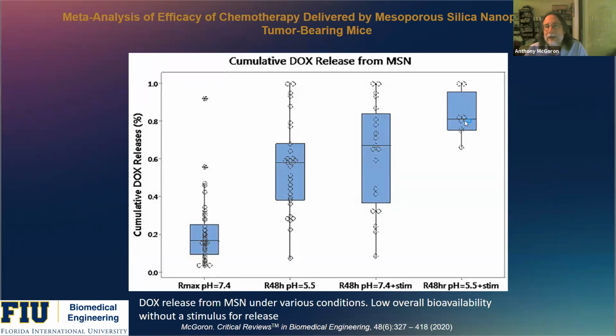If they make it into the tumor and we stimulate the tumor with heat, or maybe it's stimulated because of the thiol conjugation, so they're released due to glutathione in the cells, we get a much faster release. But remember, a very few percentage of the particles are actually making it to the cell. So if they don't make it to the cell and they don't get endocytosed into the cell, they're not going to be at this low 5.5 pH. They might be at a lower pH inside the tumor environment, but not at the very low pH that would be experienced by lysosomes inside the cell.